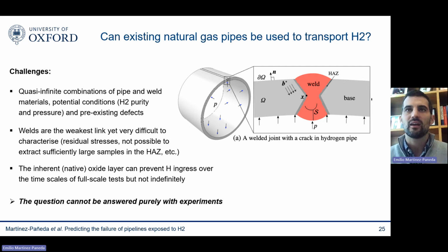That's why I think models can be a key factor here. Again, welds are the weakest link, but they're very difficult to characterize, right? How do you introduce residual stress into your lab? How do you get sufficiently large samples along the heat-affected zone to do a proper fracture test to understand what is the fracture resistance of that heat-affected zone? There are multiple challenges associated with testing welds.